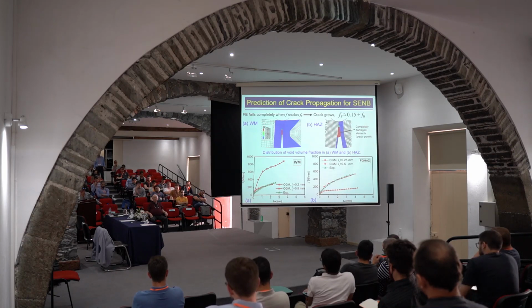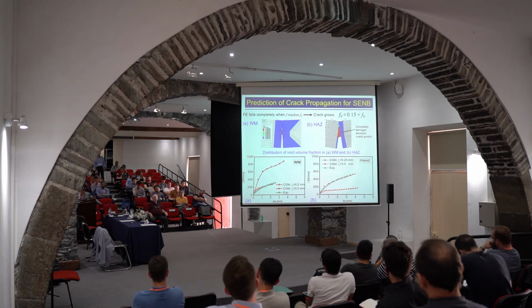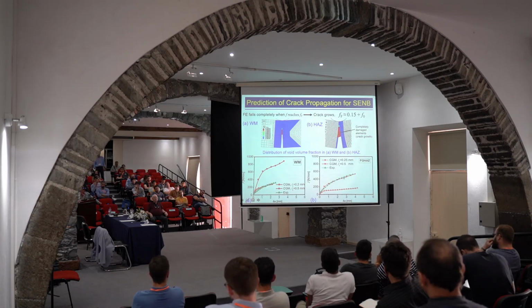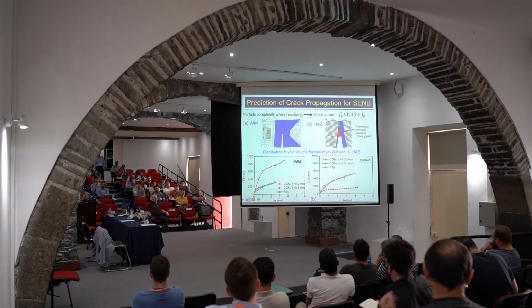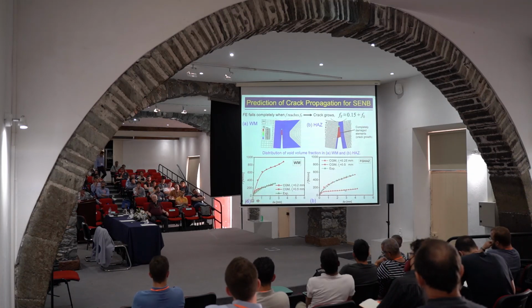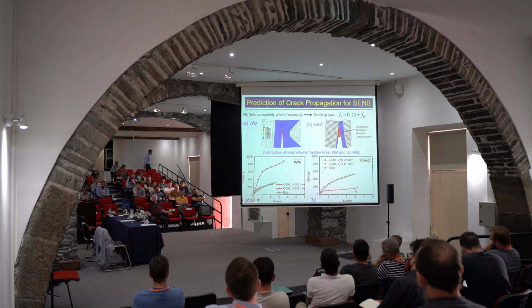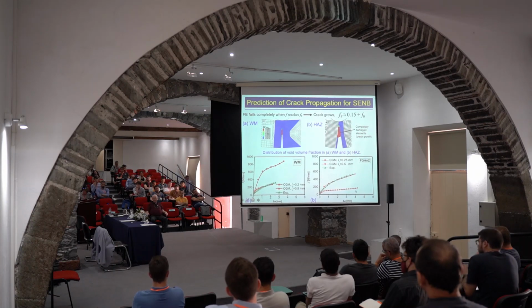Of course, people using finite element would say this is because mesh is not fine. We are actually dealing with fine mesh with a good correspondence to experimental results, and then with rude mesh, which is completely wrong. But in the case of heat affected zone, we have almost perfect agreement between experimental results and the rude mesh, 0.5 times 0.5, mesh that corresponds to lambda. And if we refine the mesh, we get something completely wrong. So there is a secret, just use lambda to construct your mesh. And don't ask why, that is up to next generation to explain.